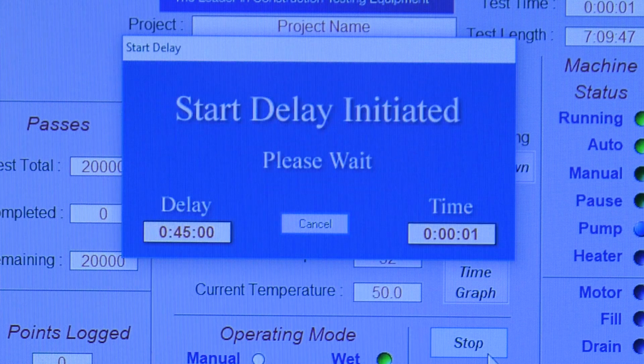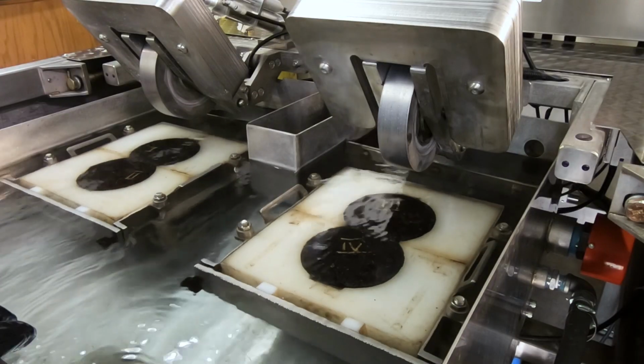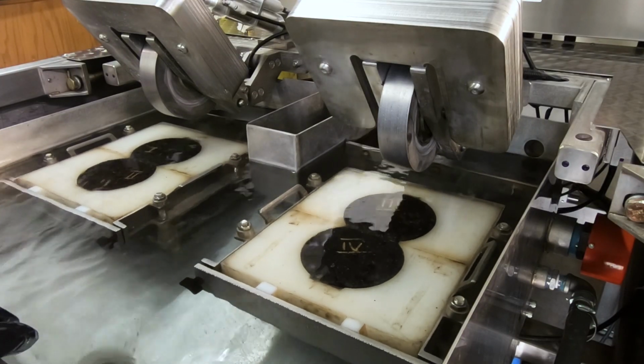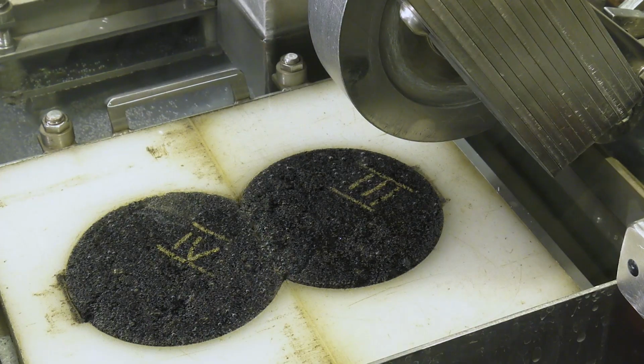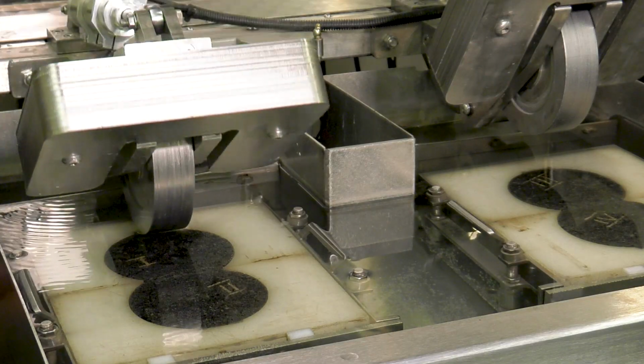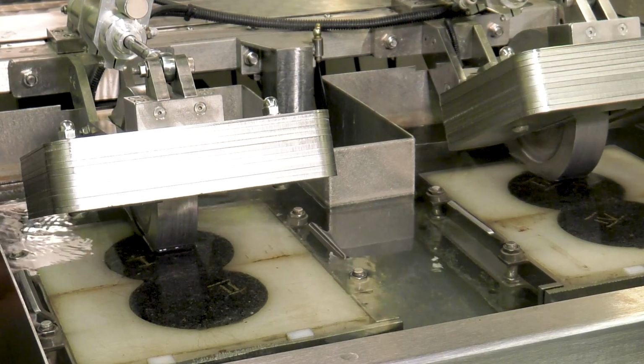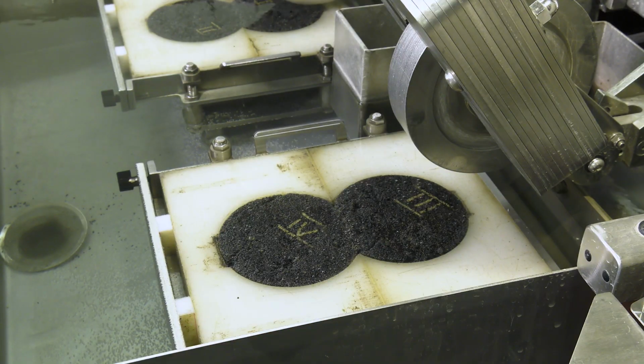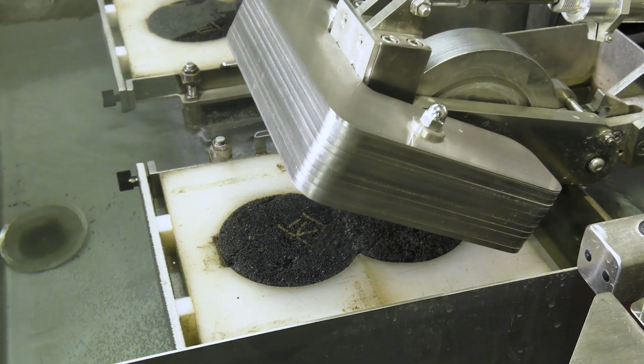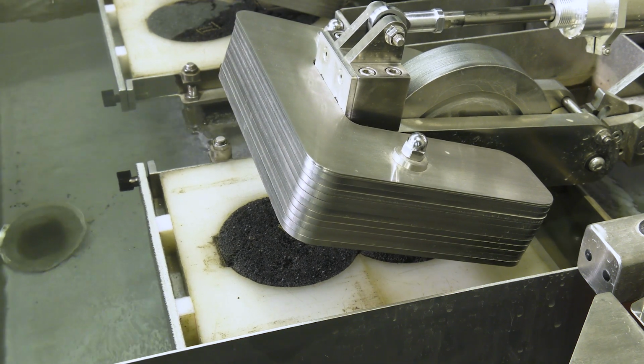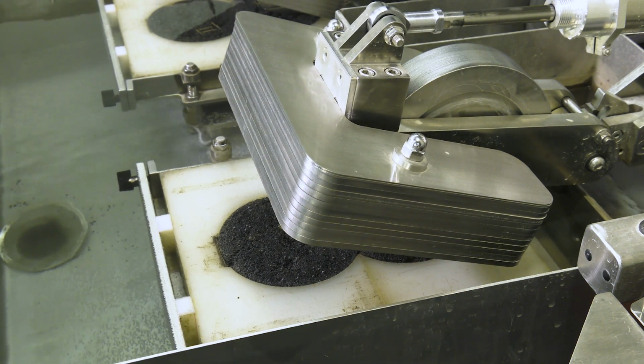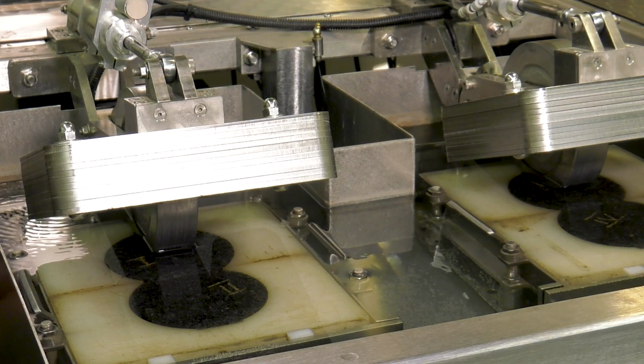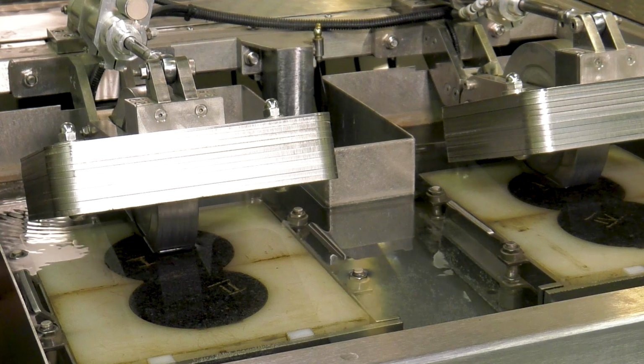Enter a start delay of 45 minutes to condition the specimens to the selected test temperature. Including the conditioning time, the specimen should not be submerged longer than a total of 60 minutes plus or minus 5 minutes before starting the tests. After preconditioning, lower the wheels onto the edge of the specimens. For machines that start automatically after the preconditioning cycle, you may lower the wheels onto the edge of the test specimens such that a majority of the wheel is in contact with the HDPE molds in the mounting tray. For manual mode, click Start to begin the test.